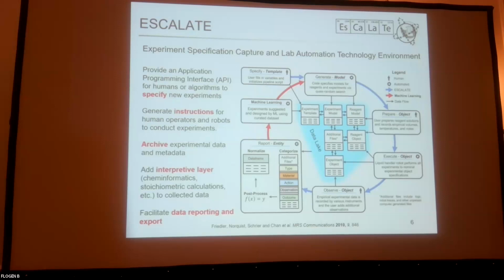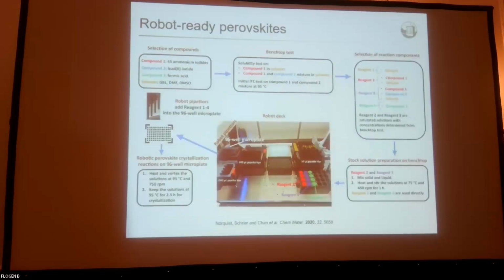And so we use this to avoid a lot of the tedious things that one would have to do by doing lots and lots of experiments. In the context of lead halide perovskites, the first workflow that we chose to look at, and all of the initial experiments for the next 5 or 6 minutes will be on lead, was inverse temperature crystallization. This is the approach where crystallization happens at high temperature. As the temperature decreases, the solubility increases. And so temperature management is an issue.